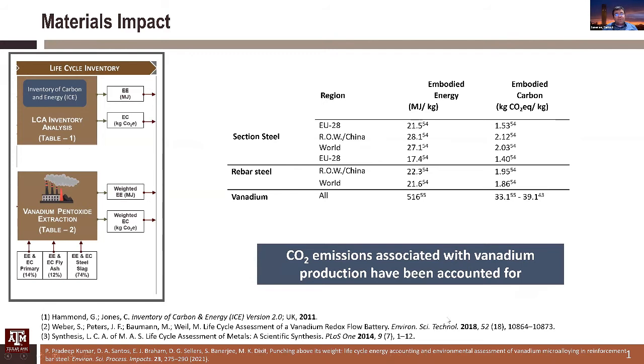So we do account for CO2 emissions associated with vanadium production. We have some pretty good numbers on vanadium production. I have to also point out that these numbers are relatively large here, 33.1 to 39.1 kilograms of CO2 per kilogram of vanadium production. This number is rapidly decreasing as our vanadium manufacturers adopt greener methods for extraction. So this is in fact going significantly lower, down to even single-digit numbers for some of the new vanadium facilities coming online.